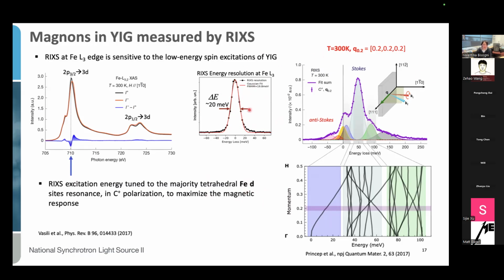For our RIXS measurement, we use an energy resolution of 20 meV. And this is a representative RIXS spectrum at room temperature and at a fixed Q, where the momentum is (0.2, 0.2, 0.2) in reciprocal lattice units. As a representation of where this momentum is compared to the surface, it is parallel to the surface of the sample, which is indeed this 111 axis here.